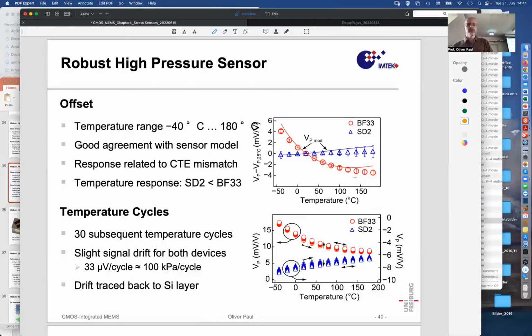So if temperature stability is a concern, then SD2 may be the choice, or some other compensation technique will be necessary to compensate for the temperature sensitivity. And such methods exist, of course. And then, in this lower part, you see that he also did temperature cycling and found out that actually there is a drift. You see here responses back and forth, and you see how this varies. One glass in this direction, the other glass in the other direction, and so this was traced at that level back to the silicon layer, but the metal actually had a lot of